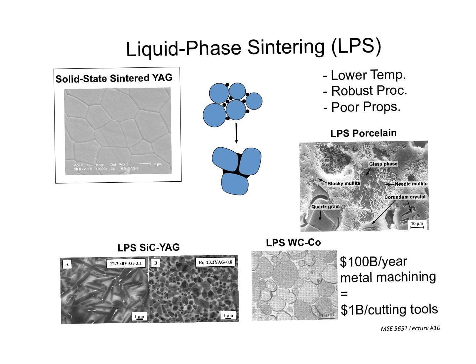All right, and so then we have liquid phase sintering, which, based on what we just talked about, probably seems like a huge relief because we can form a liquid that fills up all those pores and makes this process of transport much more efficient. But you might remember when I talked about liquid phase sintering at the end, you pay. You have a more efficient densification of a system, but you end up with some degradation of the properties. And the other side of this is that not every system has a liquid phase that works to sinter it, certainly not without degrading its properties. So some things work okay. Not every system can be liquid phase sintered, but when you can do it, it's awesome.